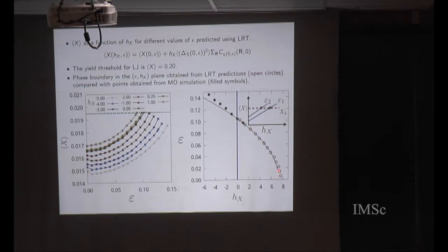These are the points, and this is the line through the points. You extrapolate this line to hit h equal to 0. And these are the yield points which you calculate. The black points are the yield points which you actually calculate in a simulation. And you can see that you have a prediction of the yield point.